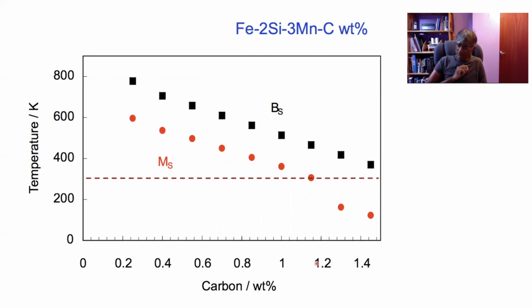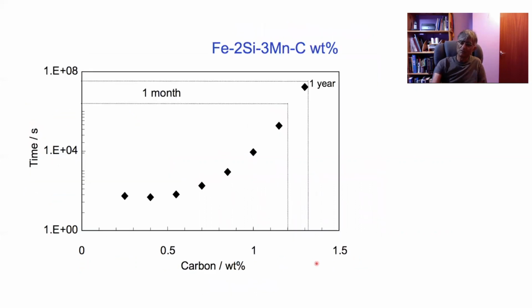There is a spanner in the works, and that is that the kinetics of reaction becomes slower as you suppress the transformation temperature. That is good as far as the dissipation of heat is concerned. But at this carbon concentration here, it would take a year for bainite to form. So you could make the steel and leave it for a year, just like wine in a cellar, and it would appreciate in value, and later on you might be able to sell it.